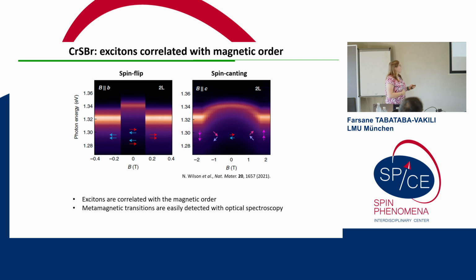And so if we apply a magnetic field along the in-plane b axis, we observe a sudden jump in exciton energy here. This is photoluminescence at a critical magnetic field where the magnetic order changes from in-plane antiferromagnetic to in-plane ferromagnetic. And if we apply a magnetic field along the out-of-plane c axis, we observe a gradual spin canting from in-plane antiferromagnetic to out-of-plane ferromagnetic, characterized by a parabolic shift in exciton energy. So this is very cool from a spectroscopist's point of view.